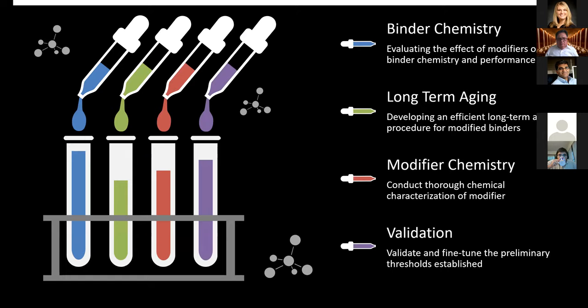The binder chemistry observes the effects of modifiers on the binder chemistry and performance. The objective of the long-term aging is to develop an efficient long-term laboratory aging procedure for modified binders. In other words, determine how much and what type of aging best characterizes and distinguishes the performance of the various modified binders. The modifiers were chemically characterized through a variety of analytical chemistry techniques. And finally, this work was validated and fine-tuned with field cores and multiple analysis techniques to ensure that the performance of the modified binders was adequately evaluated.